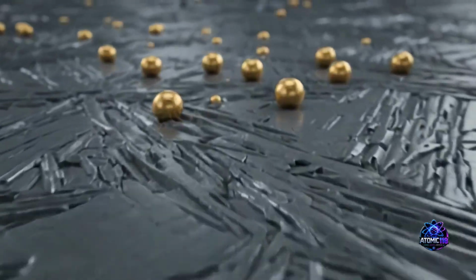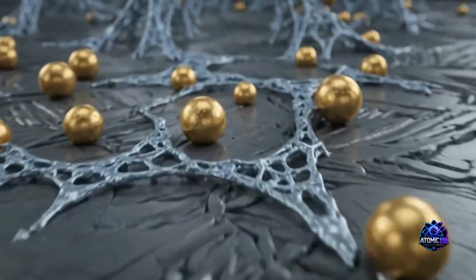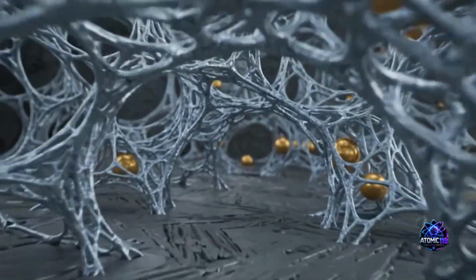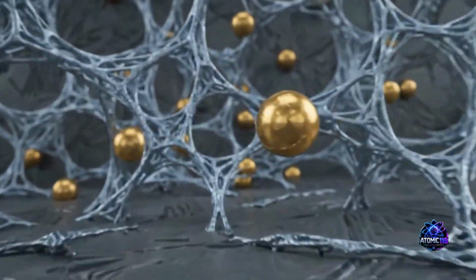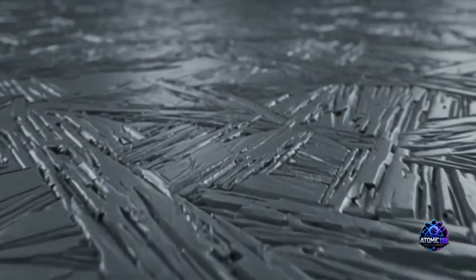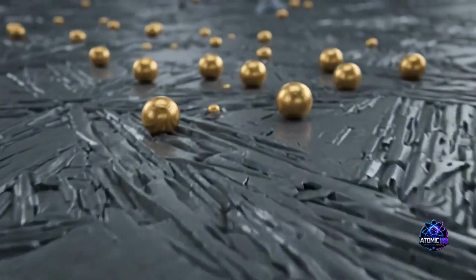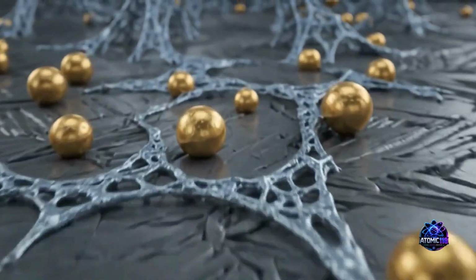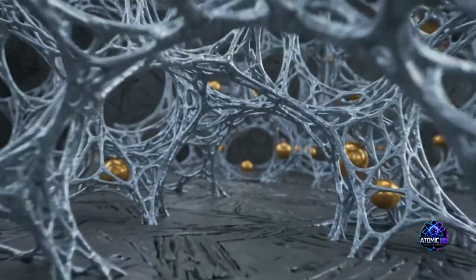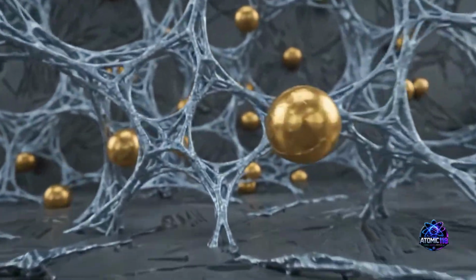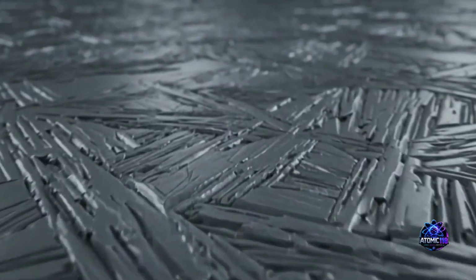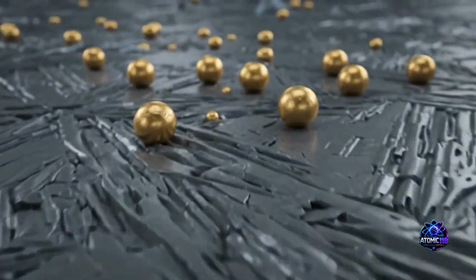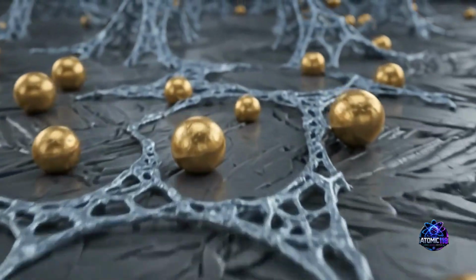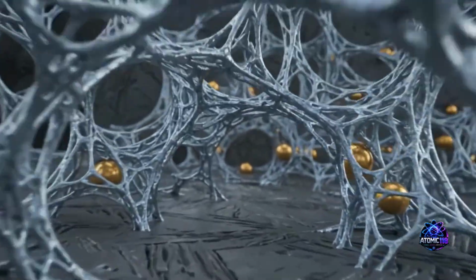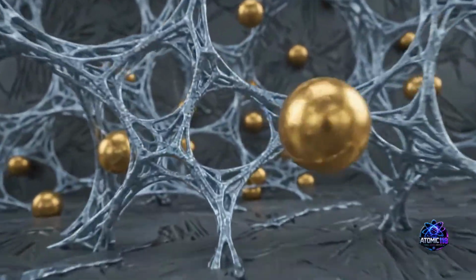Now, put a jet engine turbine blade in that scenario. Oh, man. It is spinning at tens of thousands of RPMs, constantly blasted by exhaust heat. If that blade creeps even a fraction of a millimeter, it strikes the engine housing and destroys the turbine. Which is terrifying. And this is where molybdenum's M6C carbides do their heavy lifting. Because those 6-to-1 molecular anchors act like heavy furniture placed on top of that rug. They just pin it down. They pin the dislocation lines.